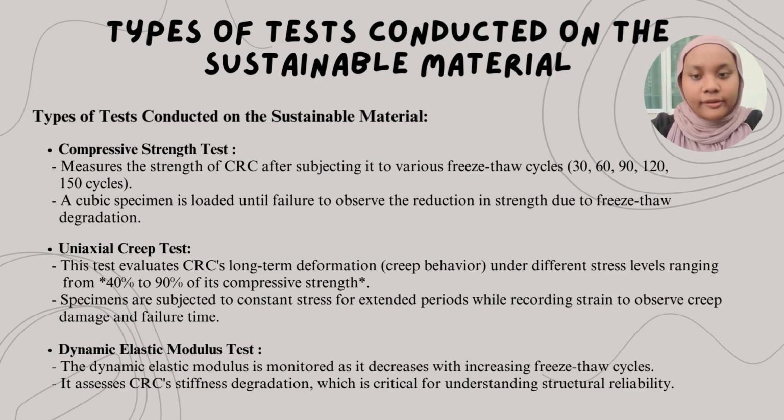Number two, uniaxial creep test. This test evaluates CRC's long-term deformation, creep behavior, under different stress levels ranging from 40% to 90% of its compressive strength. Specimens are subjected to constant stress for extended periods while recording strain to observe creep damage and failure.